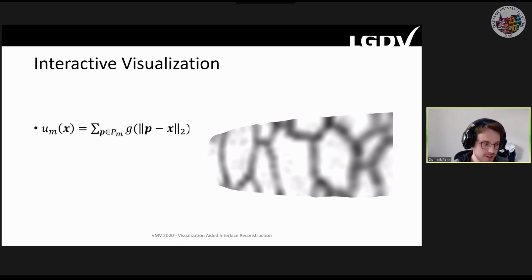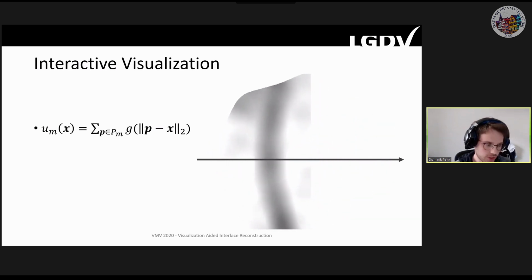And when we want to visualize it, we just do ray marching on the camera rays. So for example, if this would be a ray we're interested in, we want to find the first intersection of this ray with a boundary. We said that the boundaries are identified as local maxima in the density field. So what we do is we step in discrete fixed size steps through a ray and look until we find 2 consecutive samples which are above a given threshold. We do this minimum thresholding just to drop out maxima that are generated by noise.